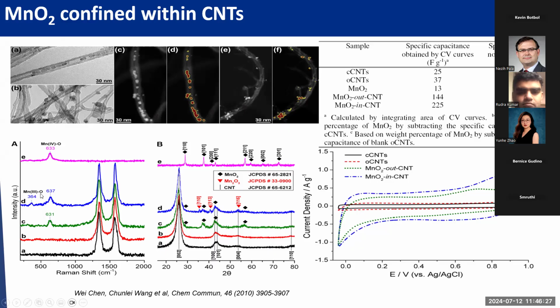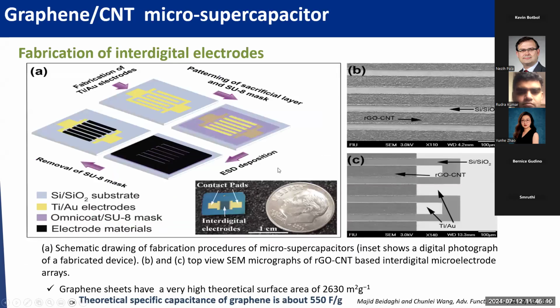So that's work from the SEM and the XRD. We can see the manganese oxide particles inside the carbon nanotube actually have both manganese(III) and manganese(IV) redox couples.